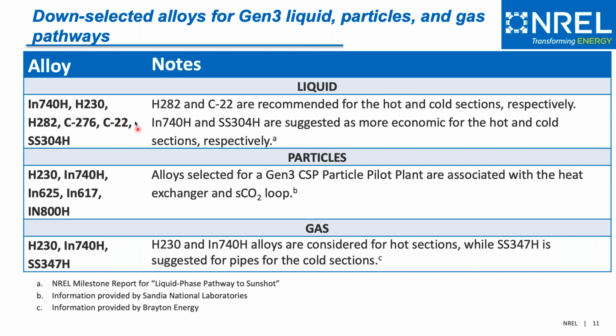These ones here are for the low temperature. And the C22 is pretty good with the corrosion, with the molten salt. And what we would like to see is, can we use the C22 in one of the end portions of the heat exchanger that is going to be exposed at 500 degrees C, and on the other end, can I have the Haynes 282?